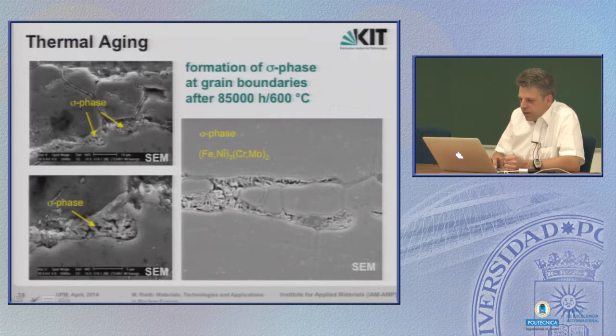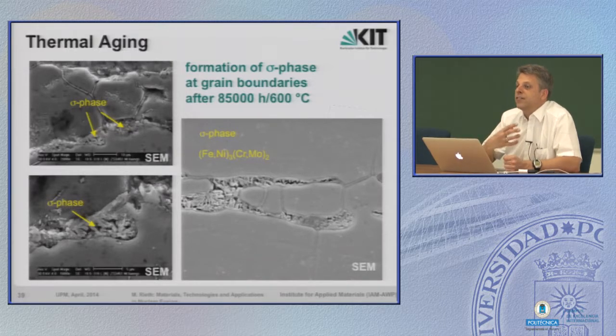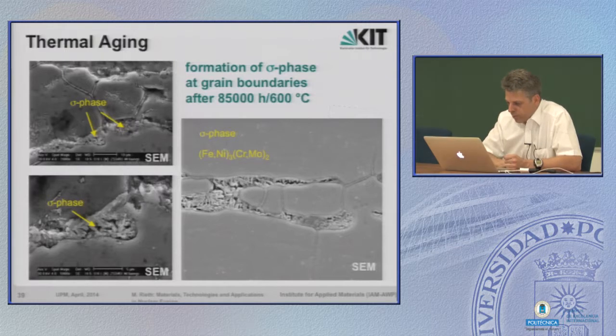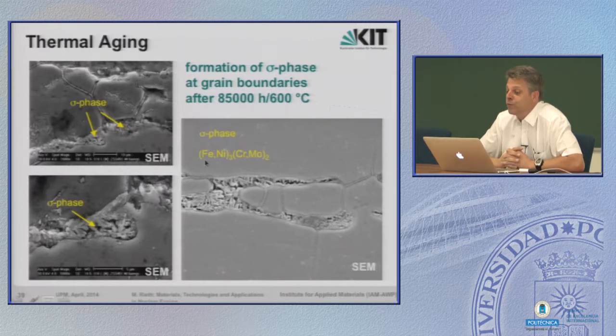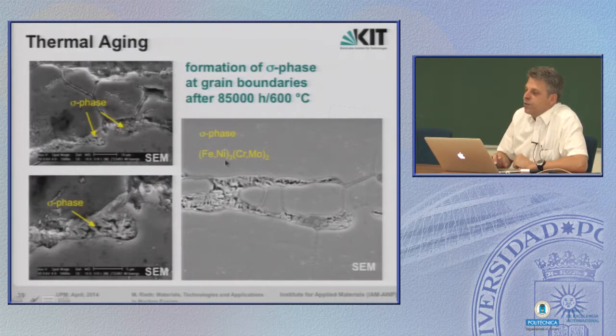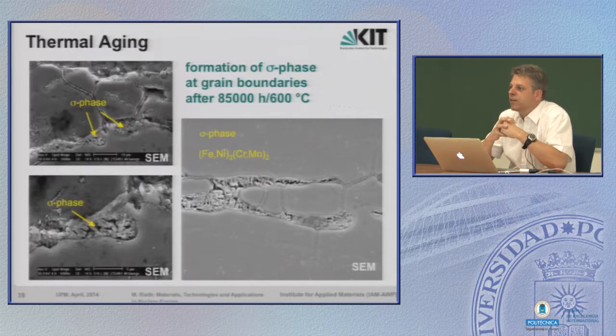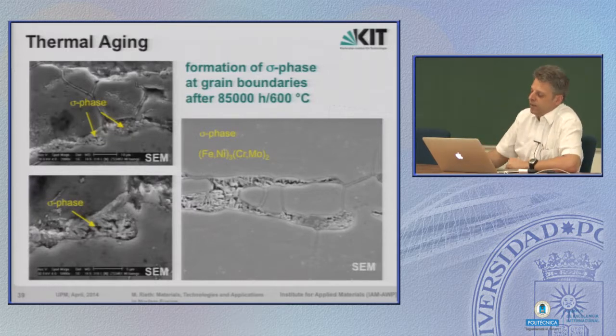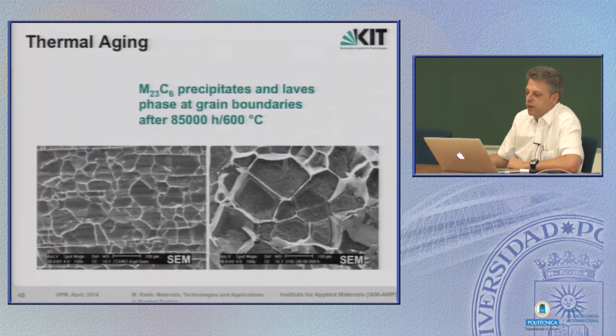And what you see here in between the former grain boundaries is again a structure which doesn't, at least to me, look beautiful, but for some microscopists it's looking quite beautiful. What it is in reality is an intermetallic phase, a mixture of iron-nickel and a mixture of chromium-molybdenum. And it takes quite a big area within the grains. This is called sigma phase, and it is a very brittle phase. So you can imagine if you have grains separated by something very brittle, then this is the place where it preferably breaks. So this aging has a very negative effect on the material properties of steels.